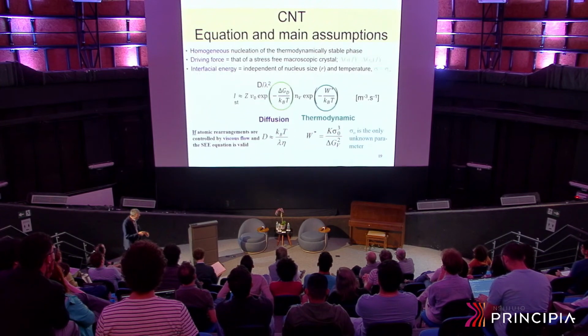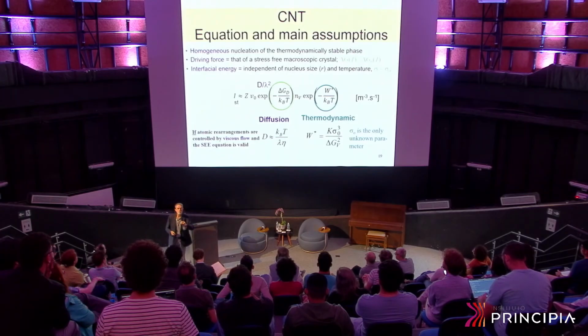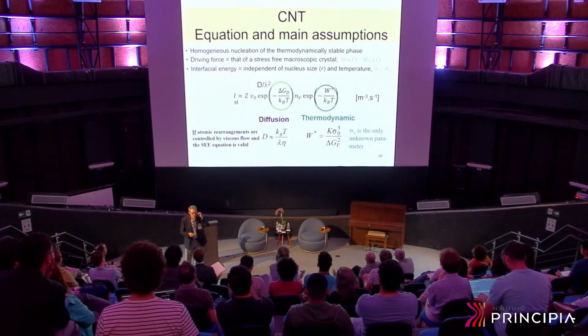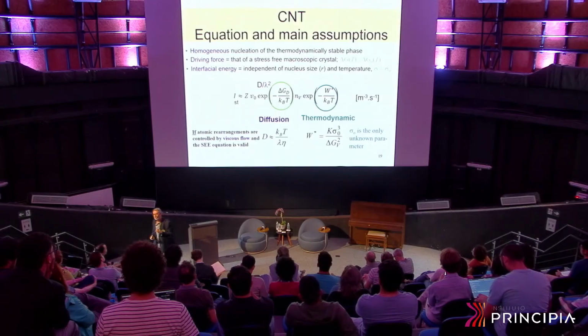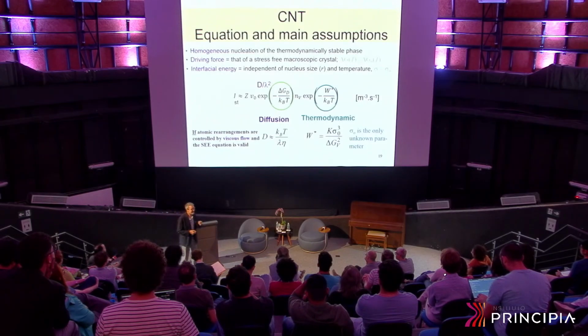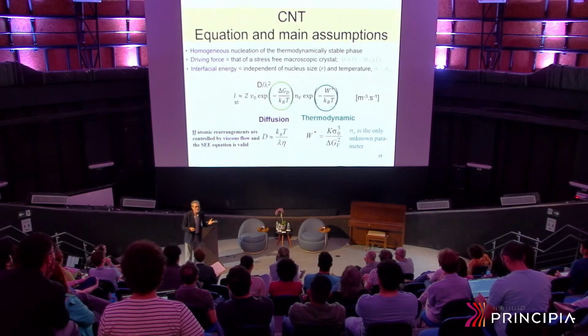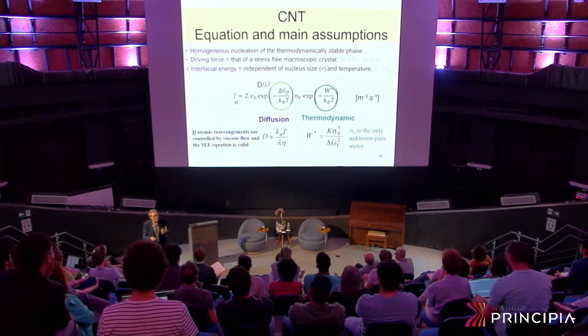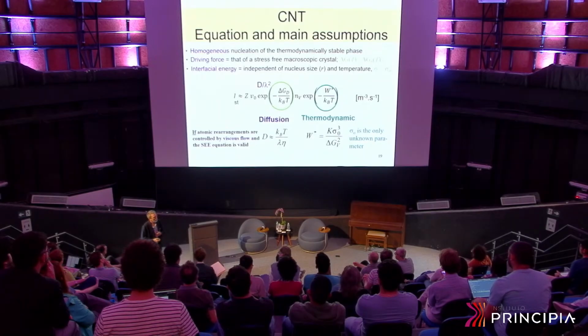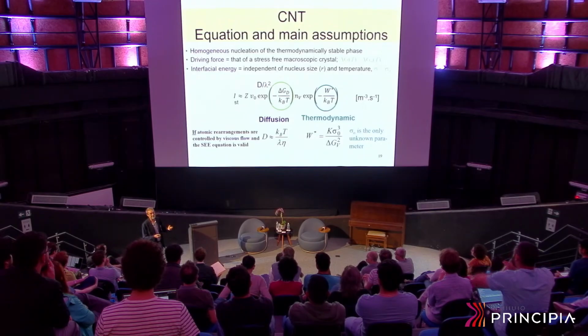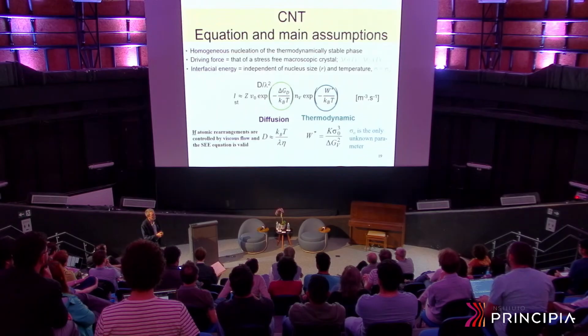the nucleation rates. However, if you're dealing with, say, pure metallic nickel, you can measure the diffusivity of nickel. You know, simple substances, there are ways to measure the diffusivity. Now, if you're working with a silicate glass with 10 components, the diffusivity of what? It's very complicated, and there are barely any data. So most people, if you're dealing with glass-forming materials, with a polymer, with organic molecules, you don't know exactly the diffusion coefficient. So most people assume that the Stokes-Einstein relation works for diffusivity also.